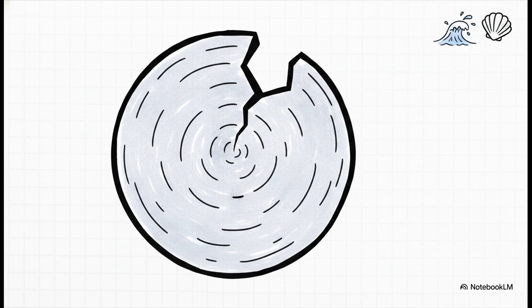These marks literally map out the progression of the crack for you. They happen when a machine goes through irregular load cycles, like maybe it runs really hard, then it stops, then it runs again. The crack actually pauses and restarts, leaving these visible rings behind. But there is a bit of a catch here. If a machine runs continuously under the exact same consistent pressure without ever stopping, you won't get any beach marks. So while they're an amazing clue when they show up, they aren't always there for the naked eye to find.